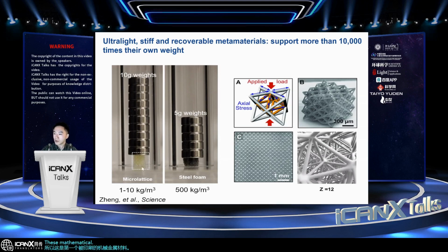This metamaterial is ultra lightweight. As you can see over here, it weighs less than 10 kilograms per cubic meter. This means it is 100 times lighter than water, but it is able to support more than 10,000 times its own weight, while also having almost zero deformation, as compared to a steel foam, where steel is a material that is much heavier than these microlattice structures, but already deforms as you show here.